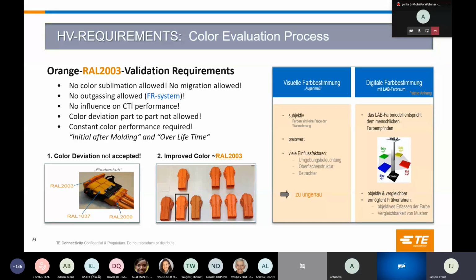Coming to the topic of orange, we had a lot of issues to be solved over the last 2 years. First, we had the combination for our parts. You see that in this color combination, where we had natural materials in place, and we had the use of master batches, also due to the fact that pre-colored materials in orange were not available on the market some years ago. We had first the solutions, natural materials versus master batch coloring at the press. In that case, with different suppliers, and based on the design, tool design, machine equipment and master batch dosage, we found out that we have a different color deviation depending on the part.